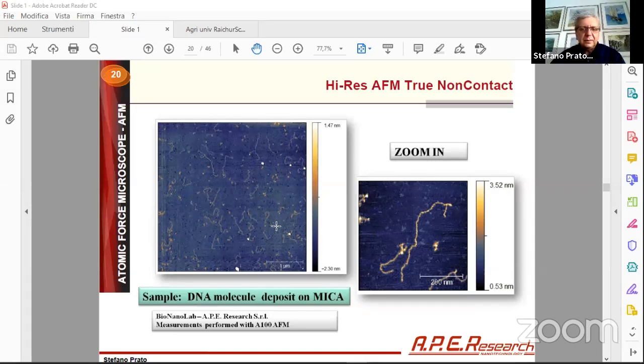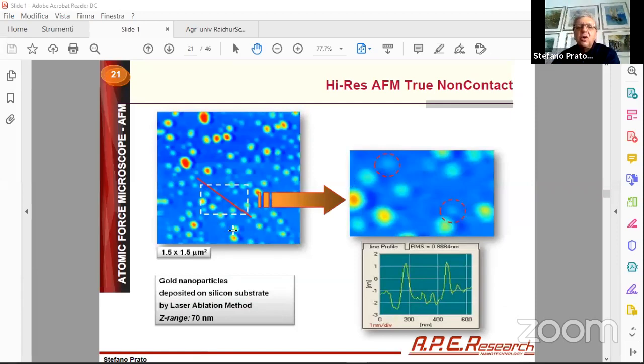This problem is not only for DNA but also, as I showed you, for fertilizer, also nanofertilizer. When you have some soft molecule, small and soft, then sensitivity is a very important parameter, because otherwise you are not able to watch what you want. Again, this is another example of nanoparticles. Those are gold nanoparticles. Okay, this is a zoom. You can see here in the red markers those nanoparticles; if you do a cross section, those are 2 nanometers in height. Gold nanoparticles are very peculiar because if they are not protected by some lipid layer to isolate them, they try to coalesce.